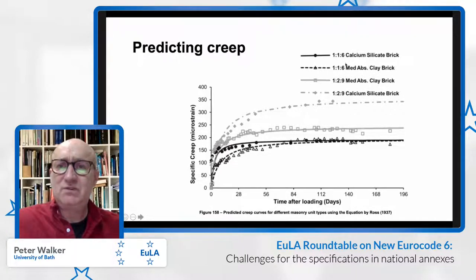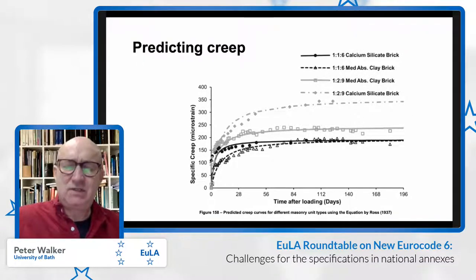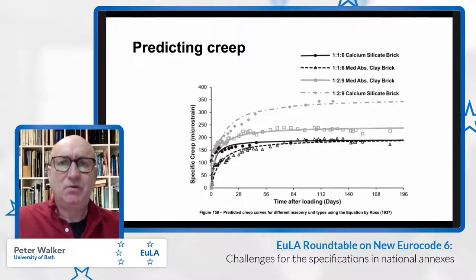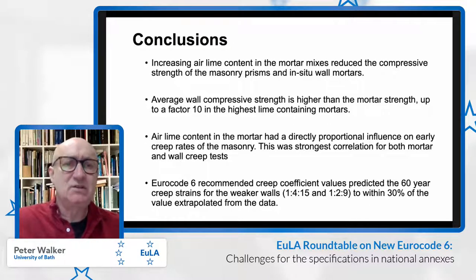And these are presented for a slightly different range of tests as presented in the previous graph. In terms of the predictions by the Eurocode 6 recommendations, which is based on the masonry unit type and the elastic modulus of the material, which we measured, although I've not reported here, it was able to predict the longer term creep within, as you'll see in the final concluding point here, within about 30% of the value extrapolated from the data.